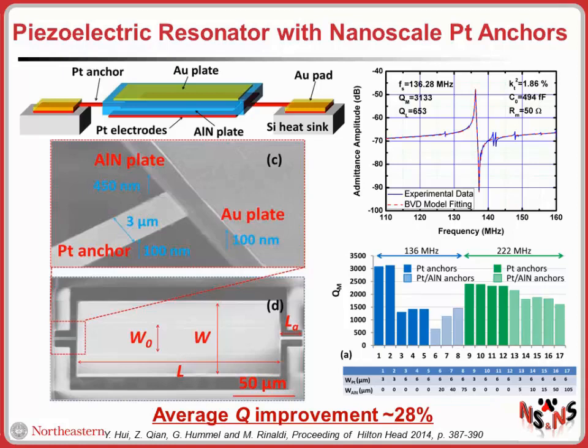So we measured the electromechanical performance of the device. Here you see the admittance curve of these prototypes, and you see the quality factor is quite high, on the order of 3,000. What is even more interesting is that we built about 17 devices, and we looked at the quality factor of devices with metal anchors or with more conventional piezoelectric anchors, like thicker anchors. And what we noticed is that there is an average Q improvement of about 28%.